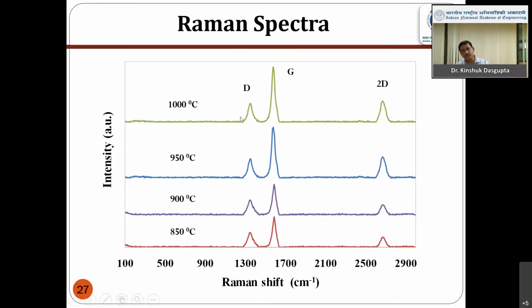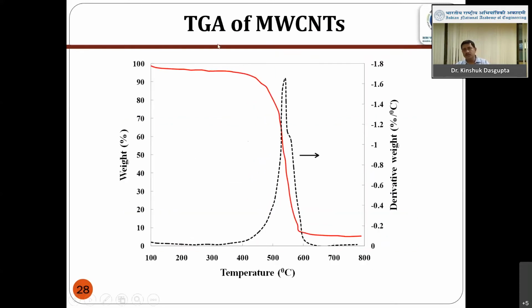If D is low with respect to G and there is a 2D peak, then we can say this is carbon nanotube. But depending on the D intensity, we can tell whether it is single wall or multi-wall. We also do thermogravimetric analysis in an oxygen or air atmosphere, by which we can find the relative proportion of different phases. We can tell the amount of catalyst in the product, the amorphous carbon concentration, and the carbon nanotube concentration, because the oxidation starts at different temperatures.